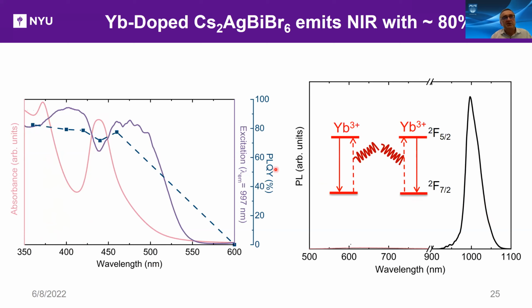What is plotted here is also the excitation spectrum. So if I sit on top of this emission and then change the excitation wavelength, the photoluminescence quantum yield basically remains about constant. And when you try to excite below the bandgap of the material, you don't get photoluminescence, which is what you would expect.